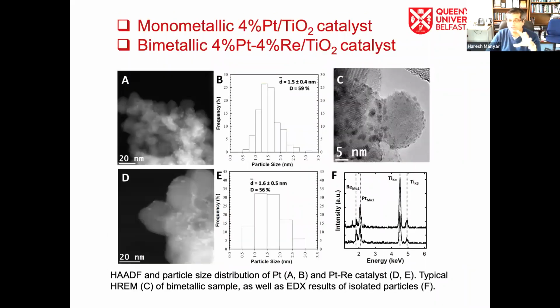different supports. Titanium was the most suitable support here. We tried platinum on titanium, on cerium, on zirconia, on silica, on alumina, and a range of different supports. And we found out that the most suitable was titanium because it's a reducible metal oxide. So it has oxygen vacancies in the lattice structure of titanium, where the carbonyl group of the molecule will sit in, and it will help to weaken the carbonyl bond and break it easily. And that is why these reactions can be done under mild reaction conditions.